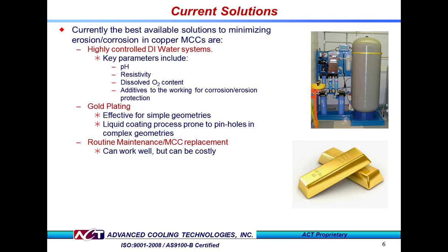Currently, the solutions for minimizing corrosion erosion defects in copper microchannel coolers are to: 1. Have a tightly controlled DI water control system, 2. Deposit a gold plating on the MCCs, and/or 3. Execute a rigorous maintenance plan and replace the coolers before they are likely to cause problems. All of these solutions have drawbacks.